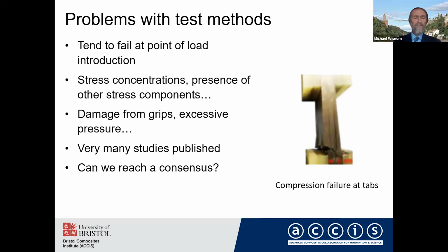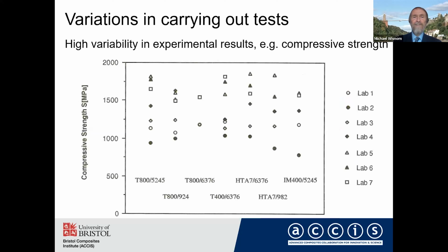Everybody's keen to do their own research, and actually synthesizing results that other people have done is not always such a popular topic, but I think it's actually very important. There's also a lot of variations in carrying out tests. So this graph here shows the results from a round robin, which was done with 7 major European laboratories, 7 different unidirectional carbon fiber epoxies, and this is plotting the compressive strength. And it's really very, very difficult to determine any trends from that data. There's so much scatter, again over a factor of about 2, and it's very hard to determine the trends of those different materials, which one is better than any other.